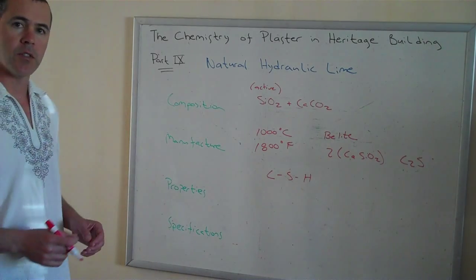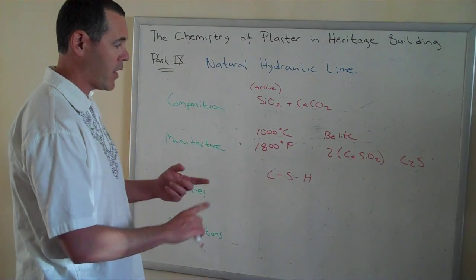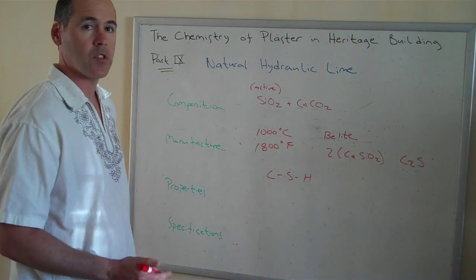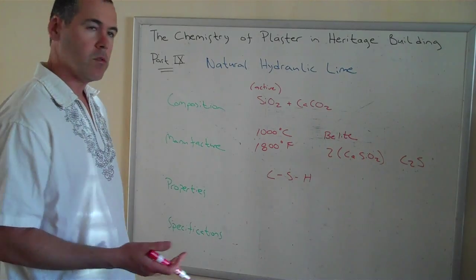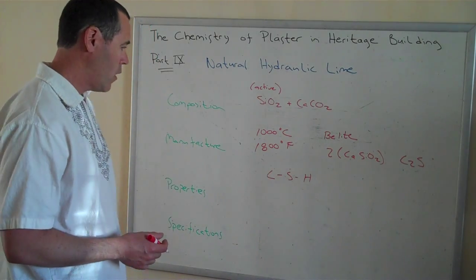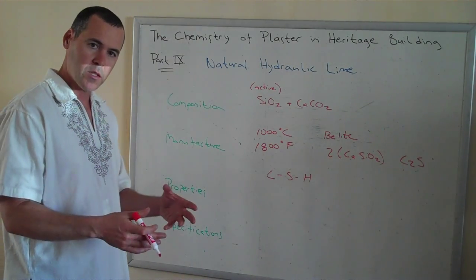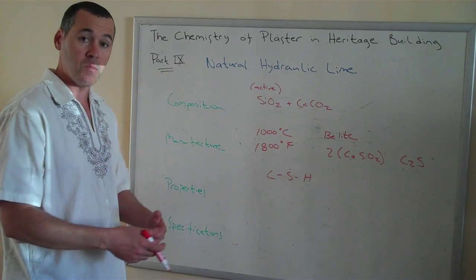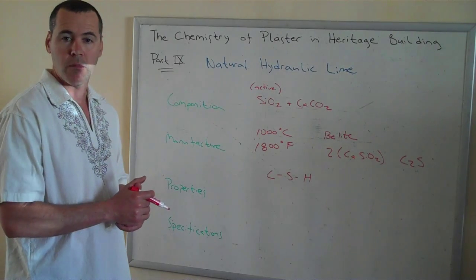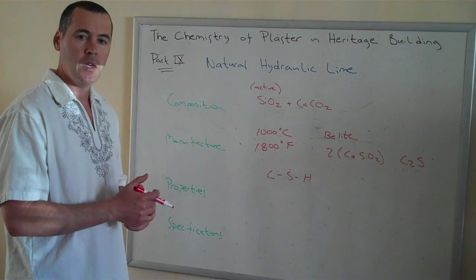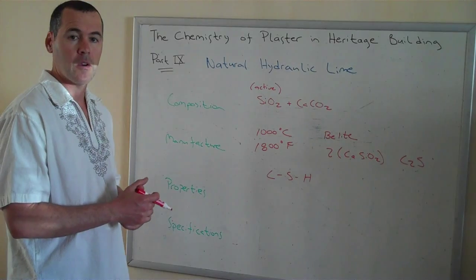There's actually a variety of different types of crystals in this family that begin growing. CSH is standing for calcium, silica, and then H is standing for water. In terms of properties — because it's hydraulic — that means if you mix it up with your aggregates to make mortars or plasters, even if you had it submerged in water, given a certain amount of time — anywhere from a day to a couple of weeks — this material will take on a hard chemical set.